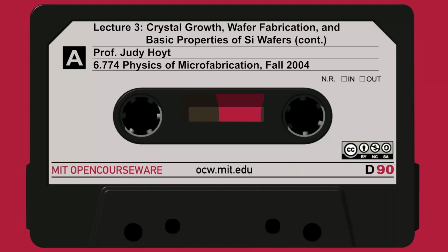We did this last time, but this is a very schematic ball and stick, 2-dimensional diagram of what a lattice might look like. Highly simplified. The vacancy is shown in this region where a silicon atom is completely missing from the lattice. You just pulled it out, and there are broken bonds associated with that. An interstitial is a little bit more complicated. There are actually 2 different types of interstitials here. There's one shown right here, and this is a pure interstitial. It's an unbonded extra silicon atom, like you just stuffed an atom into an interstitial space. It's not bonded to anything.